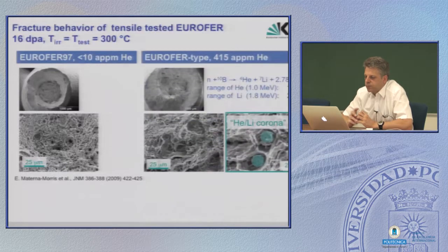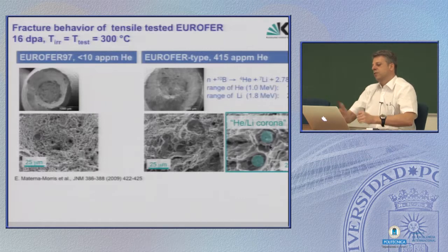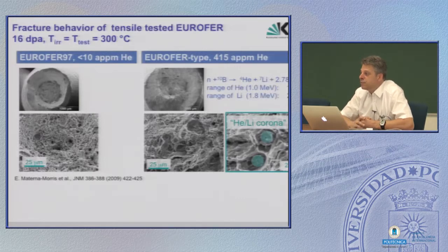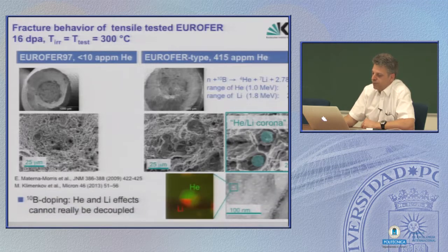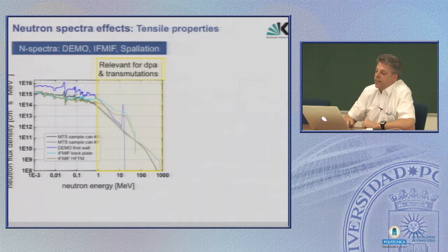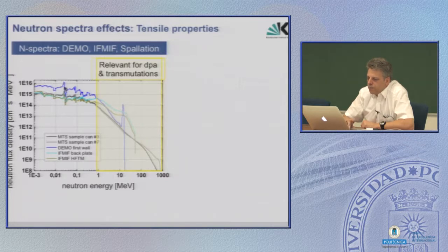Then in tensile tests, they have assessed this transmutation from neutron and boron 10 isotope into helium and lithium and some energy. And you see here indeed, as a remainder from the formerly boron precipitate, a mix of the end products helium and lithium. And this obviously is not a finely distributed defect, and these are the before mentioned reasons why many say this is an overestimation. But what we would need to determine this in a more precise way would be a neutron spectrum exactly like this blue curve.